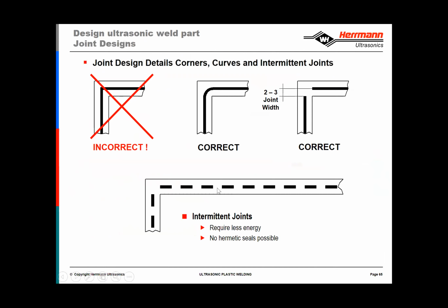Another technique for mechanical joints, not leak-free joints, of course, is to segment the energy director. So instead of a continuous energy director going all the way around, a segmented energy director can be the solution if you just need a mechanical bonding of the parts.